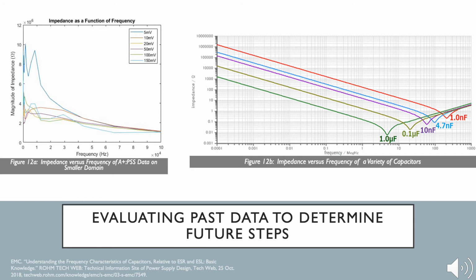The setup of the experiment had nothing outside of the composite affecting charge other than the minuscule resistance of the probes, which can be approximated as 0 for this experiment. So the results are entirely dependent on how the nano-composite interacted with charge. In this data, impedance was calculated using Ohm's law. They used the quotient of peak voltage and current to determine the magnitude of impedance. Since peak current leads peak voltage by 90 degrees for capacitors, the phase shift was also recorded.